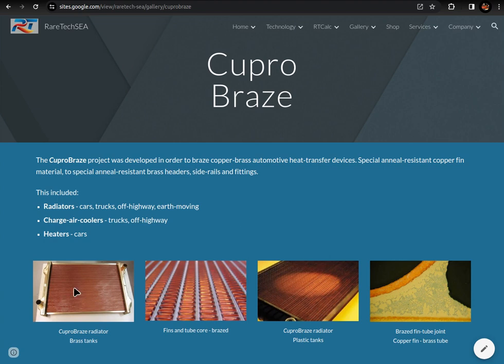So just to talk you through a few pictures, this is actually a very nice example that was made up of a CuproBraze radiator, in this case using brass tanks. Looks really, really impressive. The trick is, we did a few tricks, and I'll talk through later about my part in the program. And they ended up with a very, very bright product. To get a bright product, you've really got to know what you're doing. If you're not careful, they come across cloudy and don't look nice at all. And that's a sign that there's some level of either carbonization or oxidation.